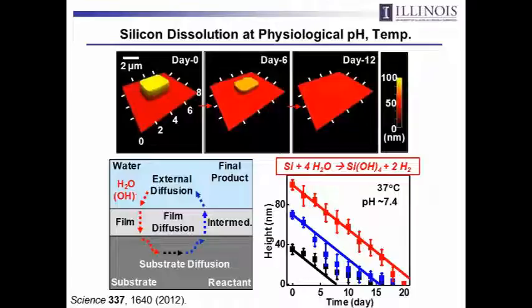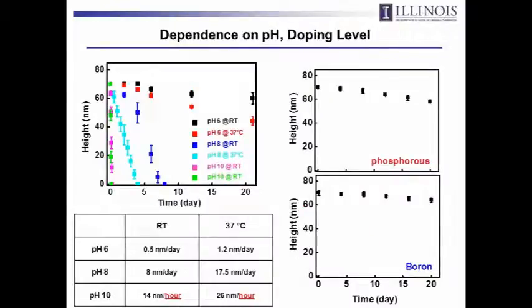And so that is an interesting observation, because if silicon can dissolve like that, provided you're using it in sufficiently thin film forms, then you can go off and build high-quality devices. Now, the detailed materials chemistry of how that's dissolving and the kinetics of the hydrolysis are extremely important, and they depend on all sorts of things. They depend on temperature. At room temperature, things are much slower than at body temperature, which might be expected.